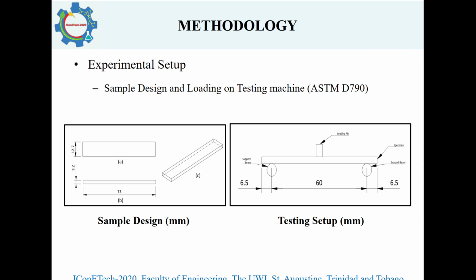So for this experimental setup, we used the ASTM D790 standard in designing the samples, as well as the orientation of the samples on the testing machine. The figure on the left shows the sample design, all units in millimeters, and the figure on the right shows the placement of the sample on the Tinius-Olsen universal testing machine, dimensions also in millimeters. On the machine, the loading pin applies a downward force, which eventually leads to the fracturing of the sample.